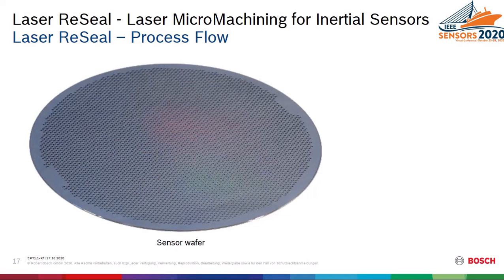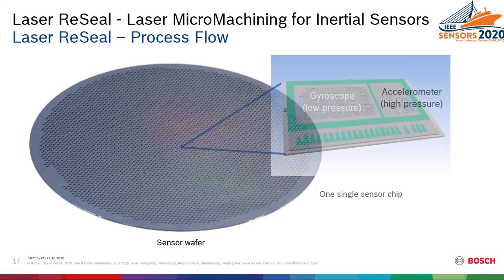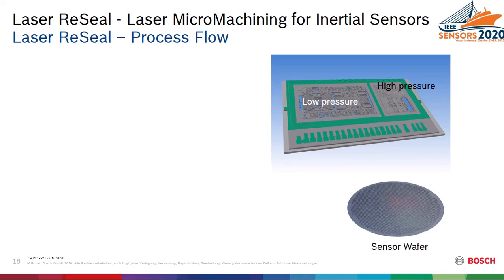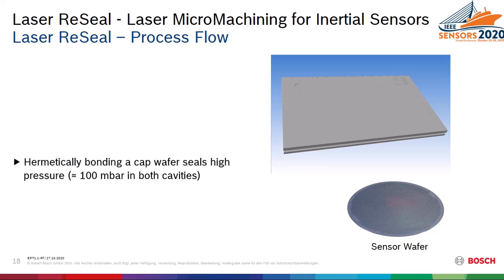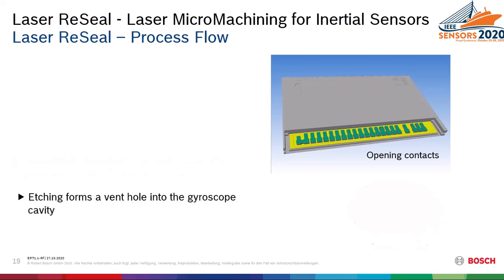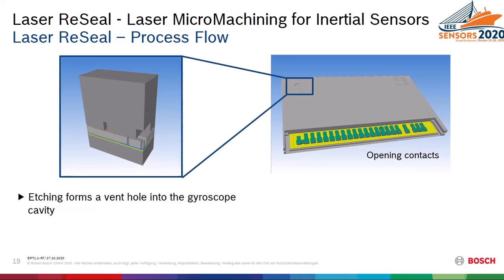You start with a MEMS wafer, and as I said, it contains several thousands of individual chips. And you can see here on the right hand side the combination of the two sensors. And as I mentioned, one needs the higher pressure and one needs the lower pressure, and this is now described. So first, the wafer will be encapsulated within another wafer by classical wafer bonding, and during this encapsulation you have the 100 millibar pressure inside both cavities. Then you will open the contacts with an etching step, and in the same step you will etch a hole into the gyroscope cavity.